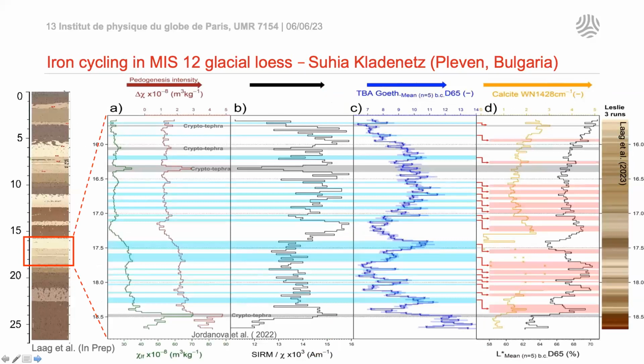So on the left-hand side, it's replotted here, the absolute difference in frequency of susceptibility in red, and then just the low field susceptibility in green. So we're going across the loess unit, so we don't expect significant variations. The gray bands on these, you can see them, but you can block them out a little bit. They're all cryptotephras. So their parameters are behaving differently, but that's expected. In the middle panel is SIRM over chi. I'll show in a couple of slides the demonstration, but at this site, this ratio is giving us information as to the parent material and wind dynamics. So as the parameter gives a higher value, wind dynamics increases.